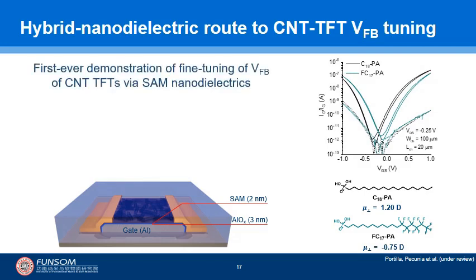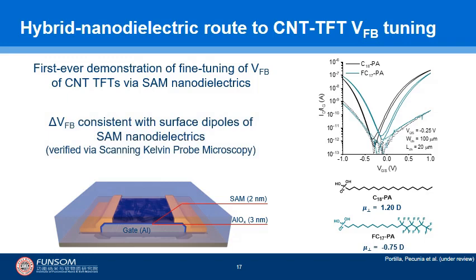While SAM nanodielectrics have been reported in the past with organic semiconductors, in fact, this is the first demonstration ever of their capability to deliver a controlled flatband voltage shift of CNT-TFTs. Additionally, we were able to demonstrate through scanning Kelvin probe microscopy that this shift directly arises from the dipole moments of the SAMs we employed.